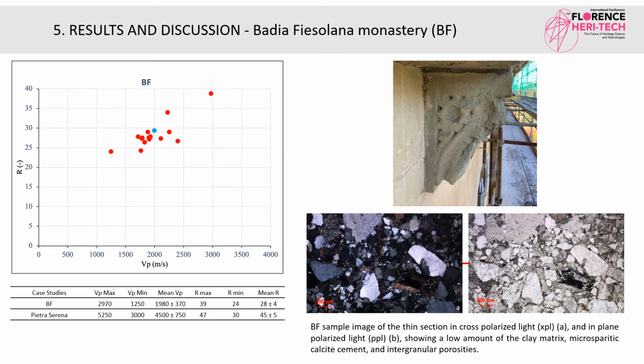The values of Vp and R of Badia Fiesolana corbels indicate medium decay, with many corbels that produce low values. The minimum values are characteristic of corbels that show numerous cracks, exfoliation, and advanced decohesion. The BF sample shows intermediate mineropetrographic and mechanical characteristics between PS and RP samples.